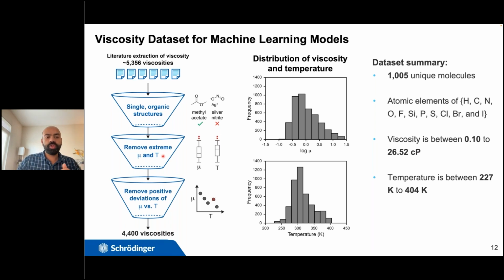And the goal here was to predict the viscosity of any molecule at any given temperature. So at the end of the day, we had a data set of more than 1,000 molecules, unique chemistries. And this is the chemical space of these molecules. And the viscosity of these molecules ranges from 0.1 to around 27 centipoise.